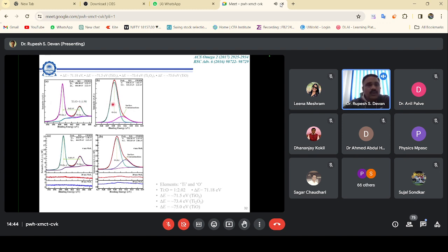So for independent TiO2, when we scan with XPS, we realize it remains approximately a 1:2 ratio. When we are on the 4 nanometer sample, the TiO2 signal was exposed because out of 10 nanometer, 6 nanometer was TiO2 and 4 nanometer was MoS2. So out of this 10 nanometer, TiO2 exists in larger quantity. So you can see here, the TiO2 signal still exists. When we move to 20 nanometer, then definitely TiO2 is suppressed because the upper layer in 10 nanometer is MoS2. So we couldn't get a signal from this Ti and oxygen.